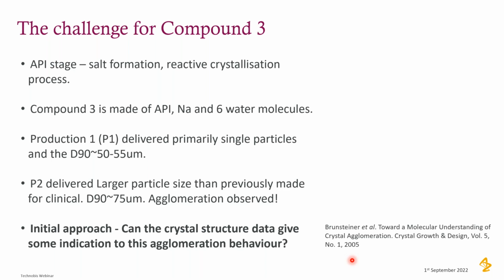During production 1, what happened is we delivered primarily single particles, and from our particle size distribution method, we got a D90 around 50 to 55 microns. But during production 2, what happened is we actually delivered larger particle size than our clinical precedents. And basically the D90 this time was 75 microns.